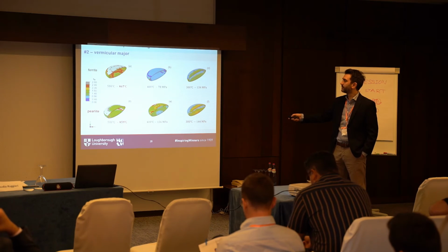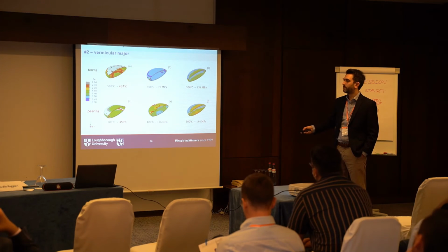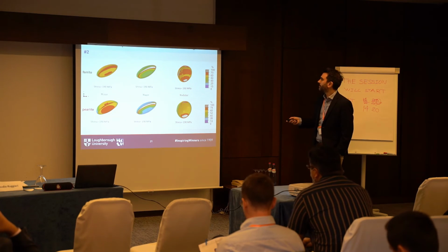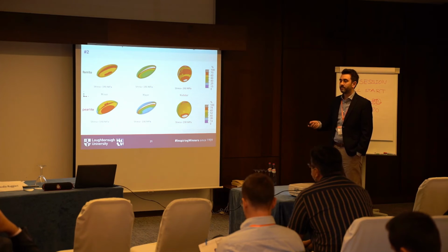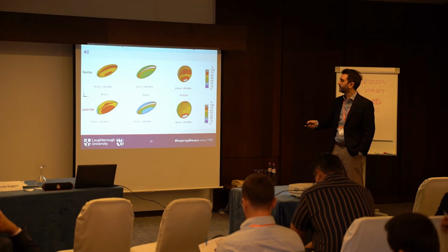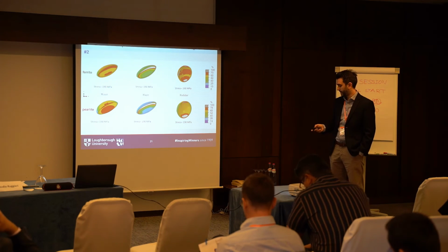In the other cases, of course, you don't observe damage, but it's consistent that you get more damage with the ferrite rather than with the perlite. And one more here, the plasticization of the matrix as well. The matrix suffers. So again, higher stresses for the ferrite ring, lower stress for the perlite.